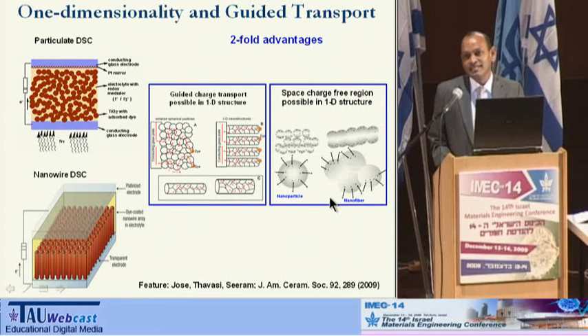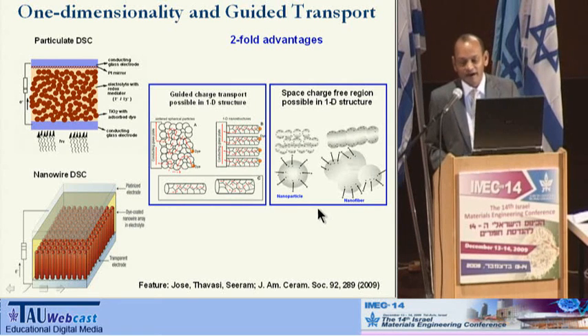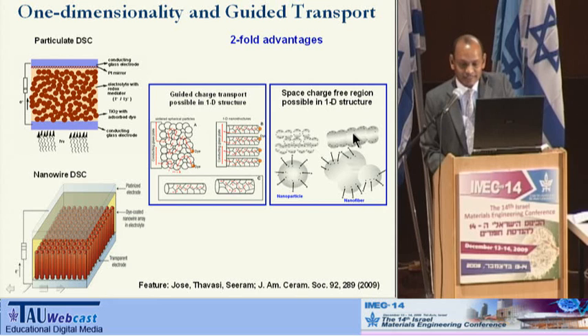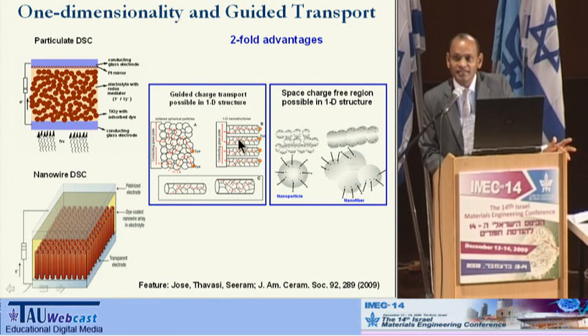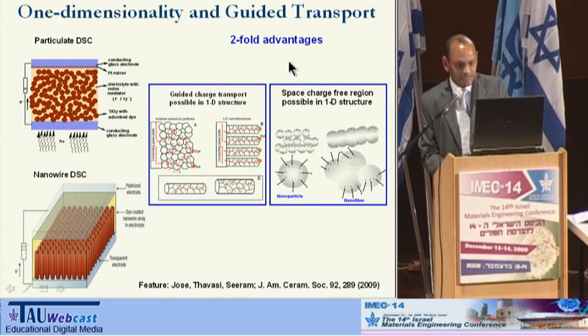The reason for using these one-dimensional nanostructures in solar cells, especially organic solar cells or dye-sensitized solar cells, is twofold. One is that, because of these unidirectional structures, we believe the space charge free region is a lot more evident in a fiber structure compared to a nanoparticle. That would give you much longer diffusion times for the electrons. Similarly, because of the one-dimensional nature of the structure, these nanorods would have a better way to tunnel electric charges through the fiber to the electrodes. So these are the two reasons why we believe it's feasible.